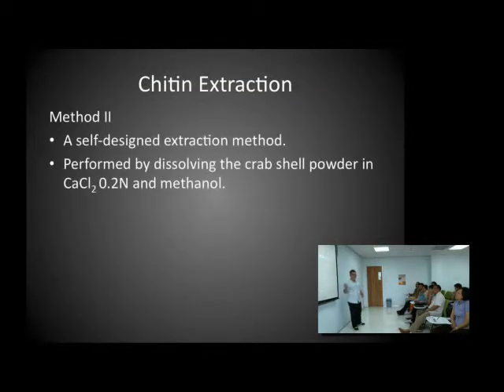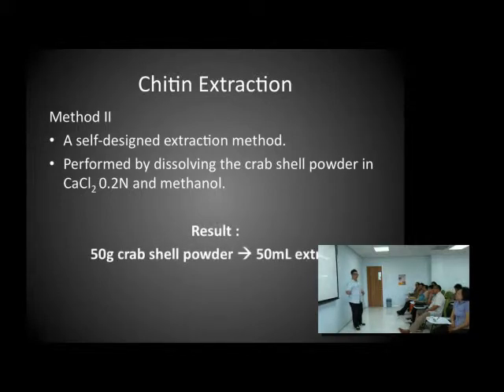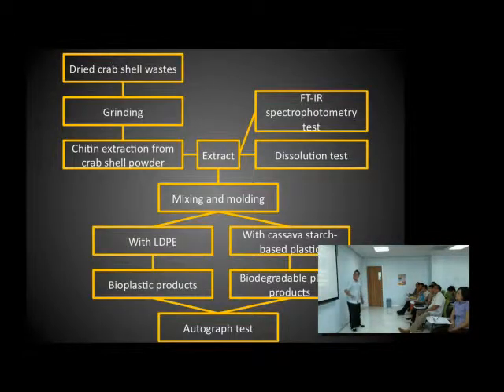The second extraction method is a self-designed extraction method performed by dissolving the crab shell powder in calcium chloride and methanol. The result is that from 50 grams of crab shell powder, I obtained about 50 milliliters of chitin extract in liquid state. Here is how it looks. It has a brown color. The existence of chitin in the extract is proven by FTIR spectrophotometry test and dissolution test.